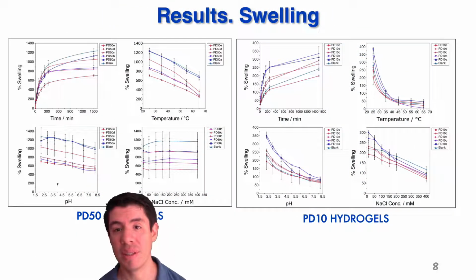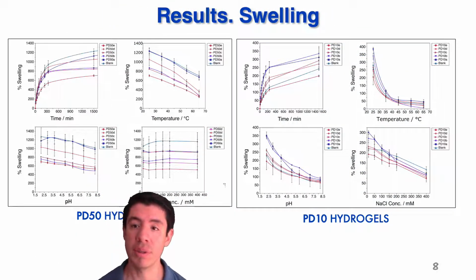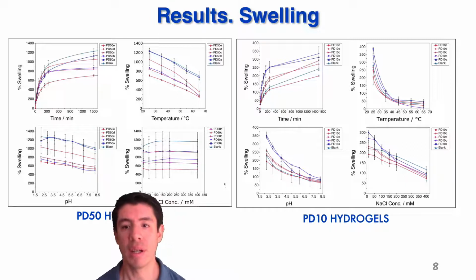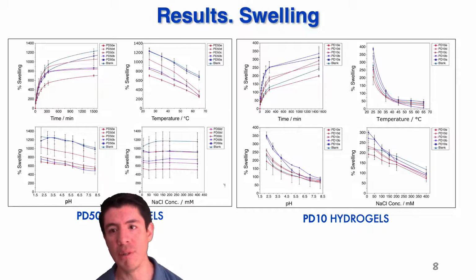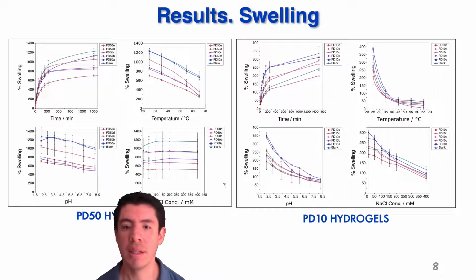The swelling ability was studied under different temperature, pH values, and sodium chloride concentrations. The hydrogel swelling abilities were influenced by such stimuli. The observed effects were more evident in the PD10 series.